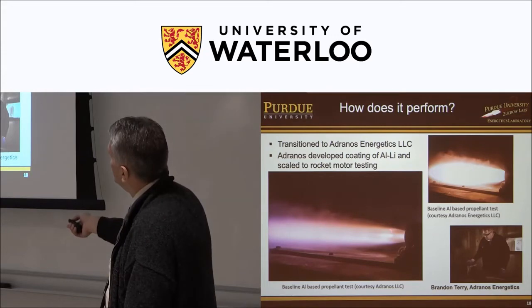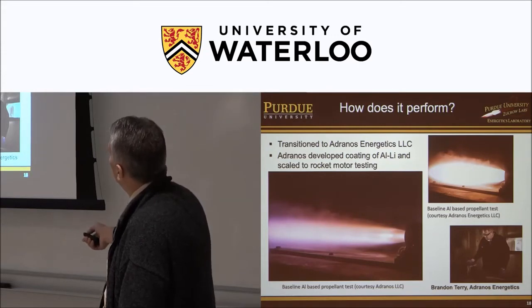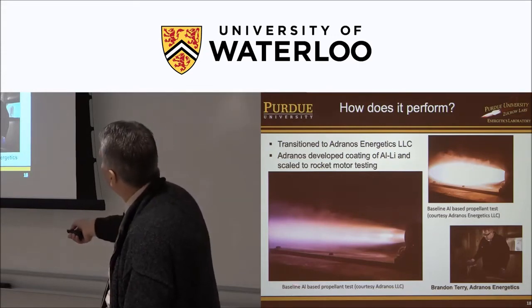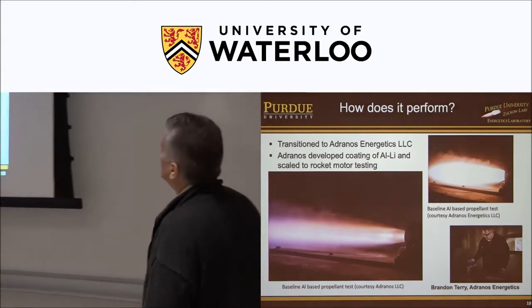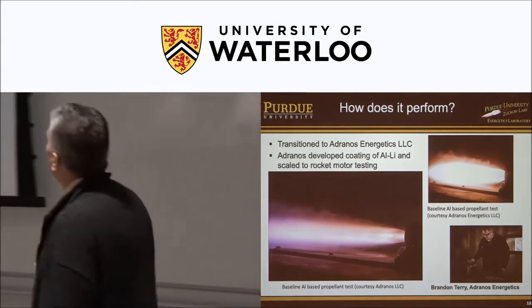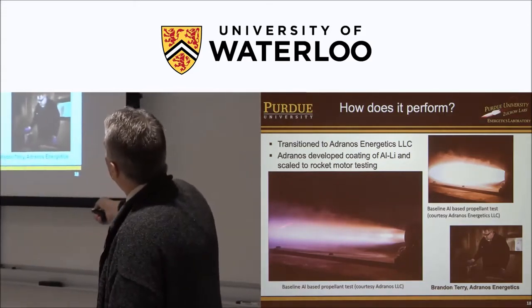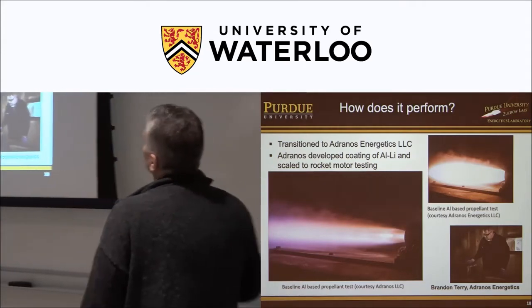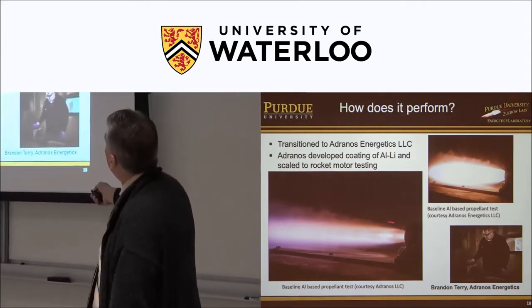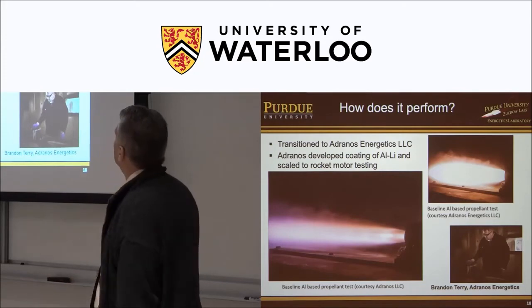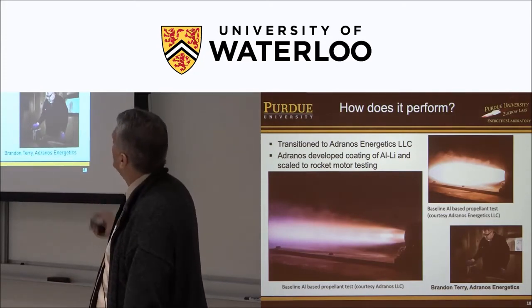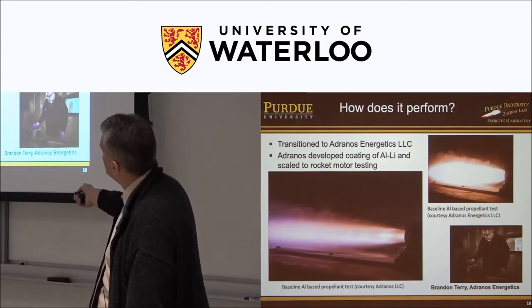In contrast, the aluminum lithium. I should have said aluminum lithium, I have a typo there. This is aluminum lithium. First of all, you see that you have the pink color. And the plume is a lot less intense. It's a little lower temperature. Plus, the particle size coming out of the nozzle must be much smaller. And you can actually see some structures here.